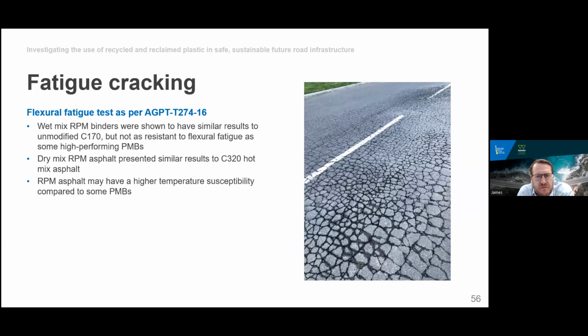Fatigue cracking is obviously of particular interest and probably the major concern when designing a pavement. So in this particular part of the study, we were considering flexural fatigue data as per Austroads AGPT T274. And the findings were generally that the wet mix recycled plastic modified binder manufactured asphalts had similar fatigue results to unmodified C170 binders or C320 binders, but were not as resistant to flexural fatigue as some of the high performing polymer modified binder asphalts, so the A10E and the A15E.